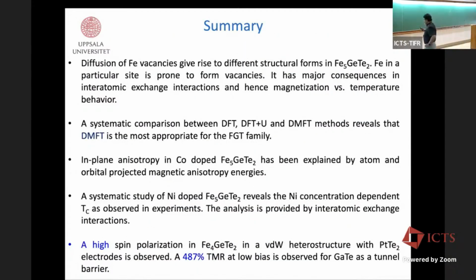Let me summarize. Iron 5 germanium telluride is a complicated system. Actually, the whole family is quite complicated. Iron 5 germanium telluride is more complicated. There are iron vacancies which move around, and also the different structural arrangements can give rise to different magnetic interactions and magnetic structures also. We conclude that DMFT will be the method of choice for these metallic ferromagnets.